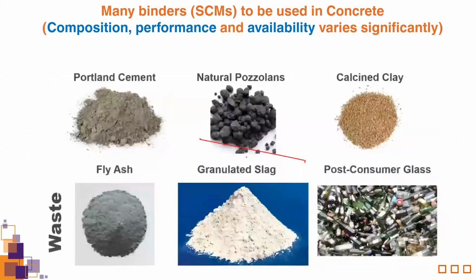So there are many binders which can be used as a supplementary cementitious material by different percentages in the concrete. The composition, the performance and availability of these materials actually varies significantly. You can see Portland cement is the most commonly used material for the production of the concrete. We have natural pozzolan like volcanic ash, volcanic pumice, zeolite. These materials have potential to replace cement by some percentage. There is a calcined clay. Calcined clay is when you heat the kaolinite clay at high temperatures, so it becomes amorphous and it can be used as a SCM in the concrete.